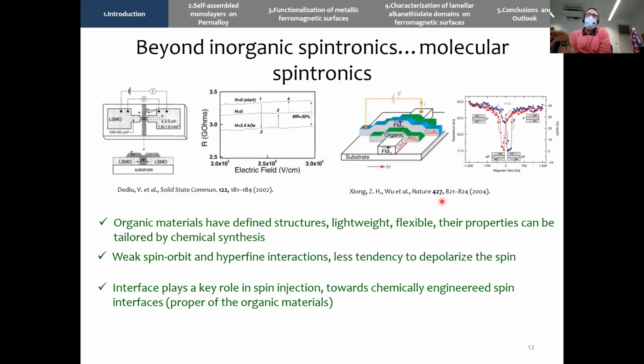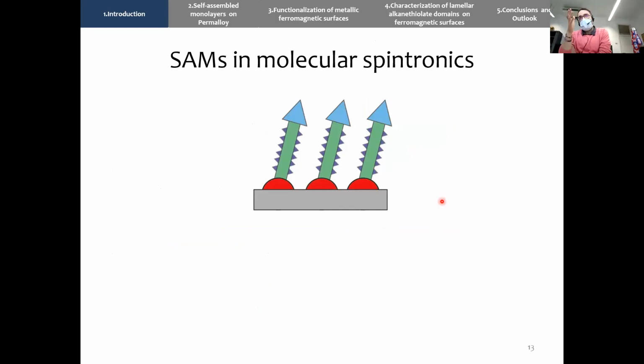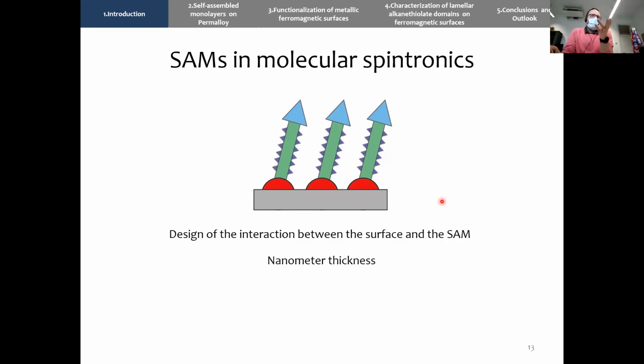And thanks to the hybridization of the inorganic electrode with the organic part of the molecule, we can create a new kind of interface called spinterface that can be chemically engineered thanks to chemical synthesis. And arriving to the point, self-assembled monolayers have been used in spintronics. As we said, we can directly control the interaction between the monolayer and the surface. They can have defined geometric thickness. They can be modular. And we can perform an active tuning and active control on this kind of interface.